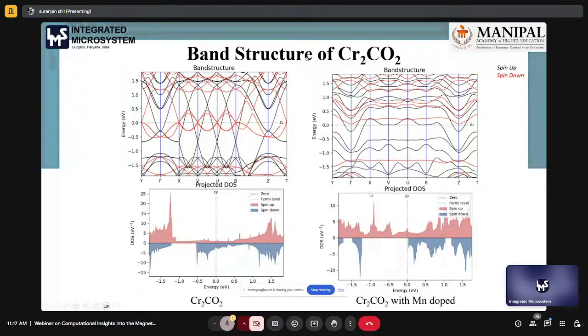Then we try to understand the band structure of this material. If we see here, this chromium carbide with oxygen termination without doping has no band gap at all. So this is conducting behavior, and we projected the density of states. We see that around the Fermi level there is always a density. But here also, in the spin up, there is a continuous band, and it's very close to the Fermi level, the density of states with manganese doped.